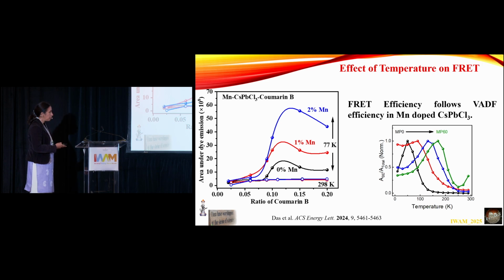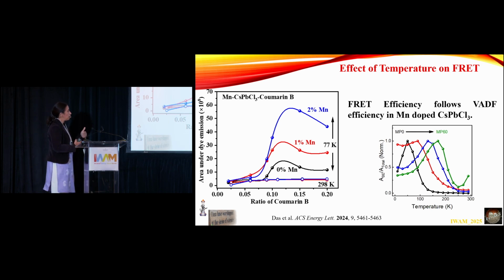So I see that when I go down to 77 Kelvin, which is below the phonon coupling temperature, I see this FRET efficiency increase. If it is above the phonon coupling temperature, then the FRET efficiency doesn't change.